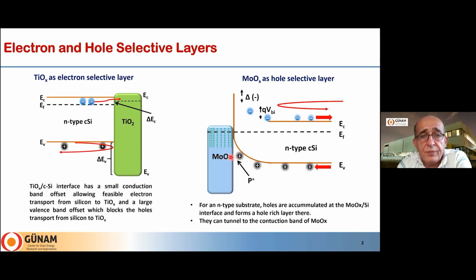Molybdenum oxide is more interesting. Molybdenum oxide has a large work function, so that we have a large barrier for the holes. But at the same time, the conduction band of molybdenum oxide becomes closer to the valence band of silicon. So we sometimes call this a broken heterojunction. It means that holes can tunnel through this interface, so they can easily move towards the material, but electrons cannot. So even though we have a large barrier in the valence band, molybdenum oxide is a good material for a hole selective layer. So molybdenum oxide is good for hole collection, and titanium dioxide is good for electron collection.